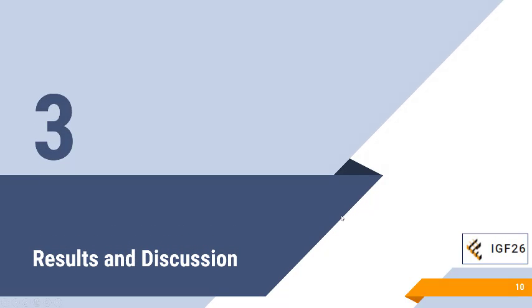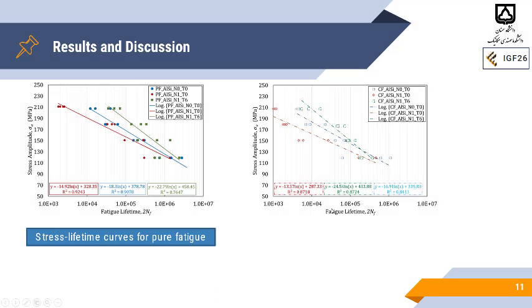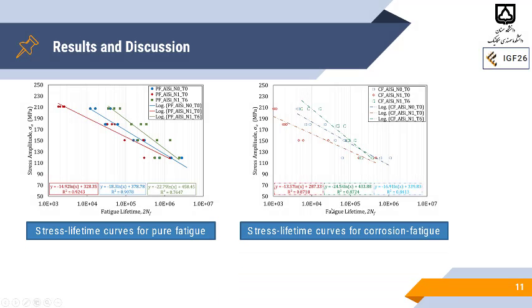What are the results and the discussion? Here, for the first result, you can see the stress-lifetime curves for both pure fatigue and for corrosion fatigue. If you check these curves, you can find that the heat-treated nanocomposite materials have higher lifetime. That was in the green lines, and here we also have the same behavior for corrosion fatigue.